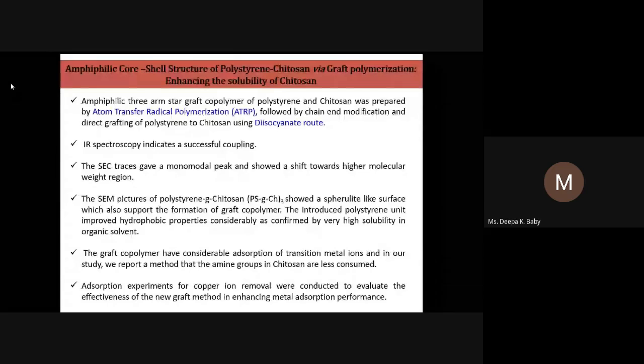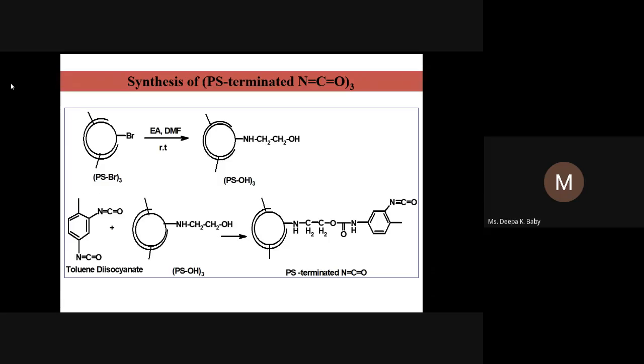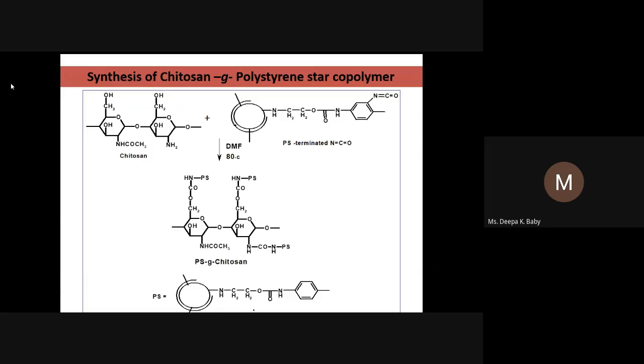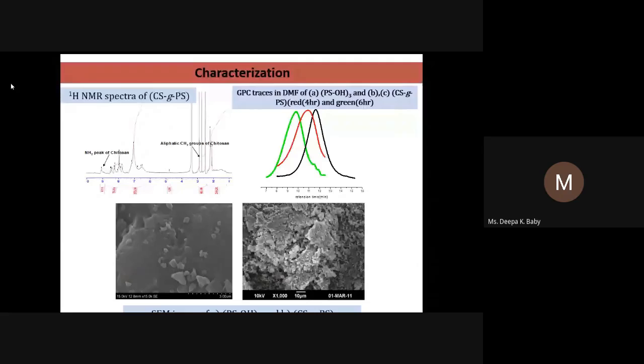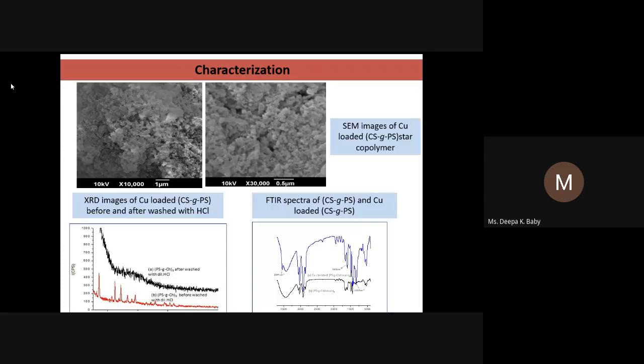Another example is the amphiphilic polystyrene chitosan copolymer. This is also amphiphilic. Polystyrene is hydrophobic and chitosan is hydrophilic, and it also undergoes self-assembly. And this is the reaction, how it is prepared. I'm not discussing it. The characterization technique we have used is NMR spectroscopy. You can see both chitosan and polystyrene incorporated. Then GPC will give the molecular weight of the compound. Some analysis also shows that chitosan is incorporated in this polystyrene.